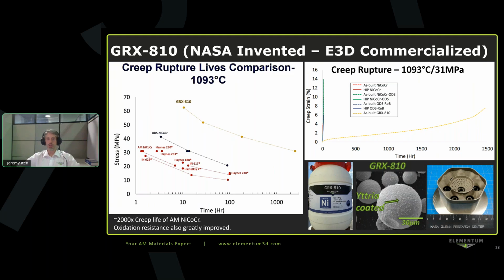So this is another example of a different approach for dispersion strengthening. I mentioned the RAM dispersion strengthening approach. This approach is actually using pre-synthesized yttria that's coated onto the surface on a nanoscale onto the other materials. Because it is coated onto the bulk materials, you don't have some of those other concerns that you might have with a free nano type powder because it's now a coated micron scale product.